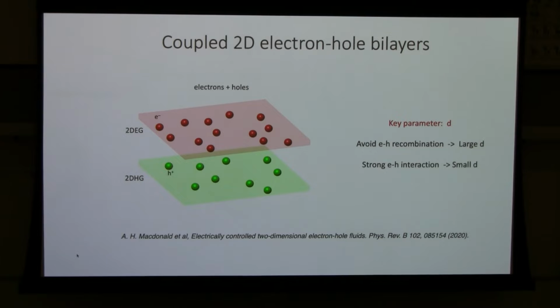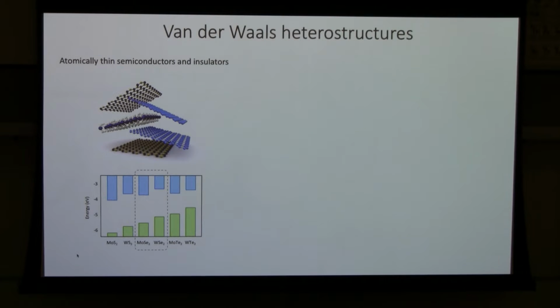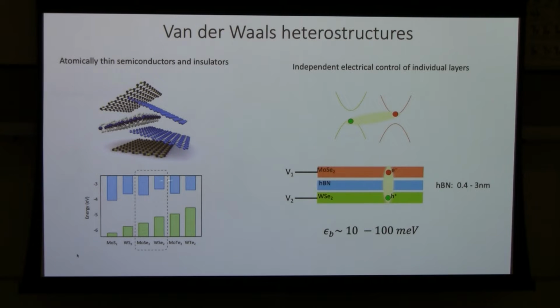So since the discovery of graphene, it turns out the best system to realize this electron-hole bilayer is atomically thin heterostructures. Because people realized that you can exfoliate many layered materials into atomically thin sheets, which can be semiconductors that can host the electrons and holes, and insulators that can form very good barriers. Furthermore, we can simply stack these individual layers together to form a heterostructure, to design basically anything that you want. And one example is the transition metal dichalcogenides.